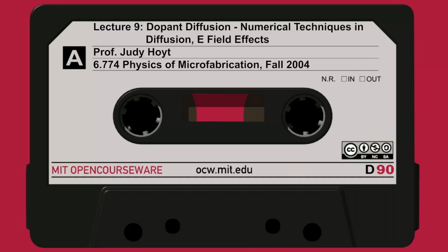What we find is that we can do this compression of this equation, and we find that the total flux F is written as minus H times the diffusivity of a dopant, D sub A, partial C, partial X. So we've been able to write down an equation that looks just like Fick's first law, but there's an H factor multiplying it. And this H factor turns out to be equal to 1 plus C divided by the quantity square root of C squared plus 4Ni squared.